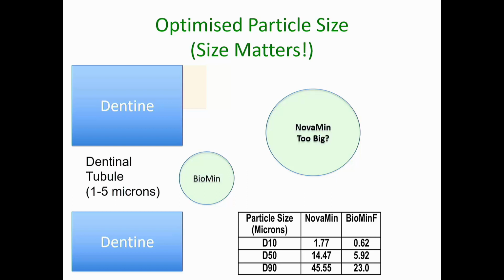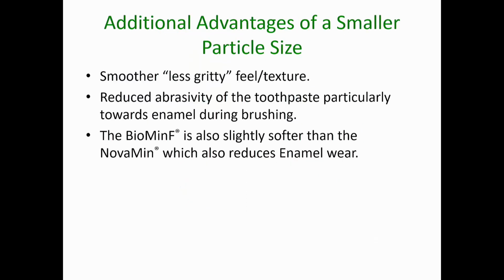The Biomin particles are quite considerably smaller than that of the Novamin particles. So the average particle size is about 14 microns for the Novamin, and it's about just under 6 microns for the Biomin F. And this means there are a lot more particles of the Biomin glass that are capable of going into the dentinal tubules and occluding them to prevent the fluid flow.